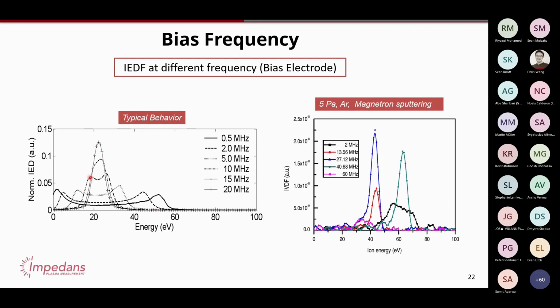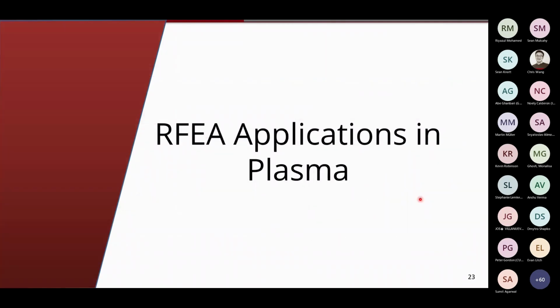Now, this is in a simple situation. There can be more complex situations. Sometimes coupling of the frequencies changes in a tool. This is data from magnetron sputtering, 2 meg, 13 meg, 27, 40, and 60. And the behaviors are all over the place. This is because in some tools, you can be in a capacitive dominated mode, or you can be in inductive dominated mode, and it can be quite complex. Usually you can model this, but it's better to just measure directly. So we're nearly at the Q&A section.